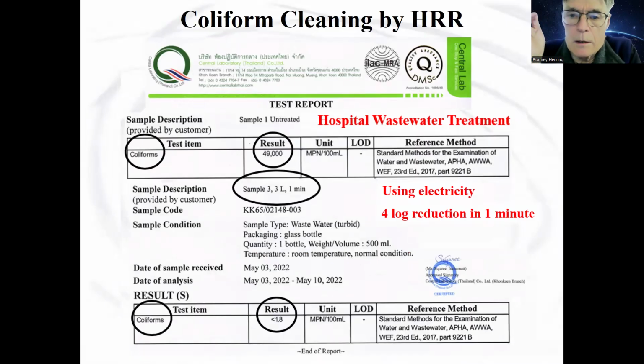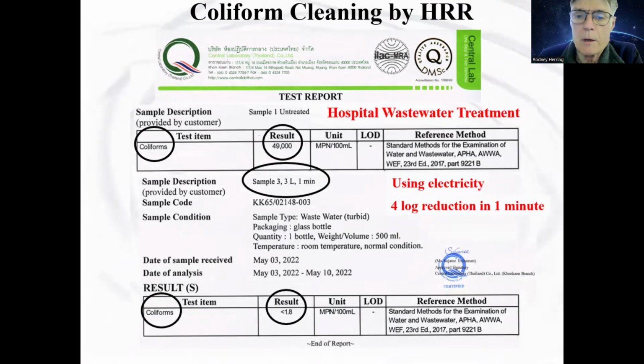There's hospitals in Southeast Asia using it for cleaning their wastewater. And we see in this official government test here, they start with 3 liters of water where there's 49,000 coliforms per 100 milliliters. After running our reactor in it for 1 minute, the coliforms are reduced to less than 1.8 per 100 milliliters. So it's very, very effective, 4 log reduction in 1 minute.